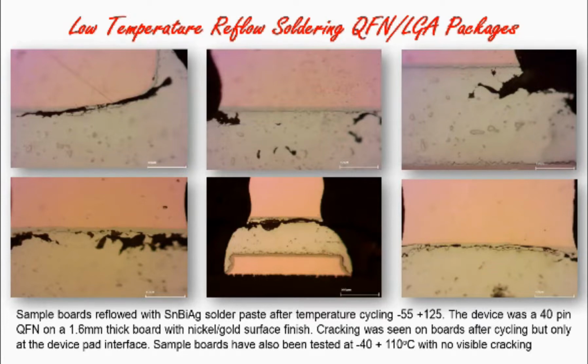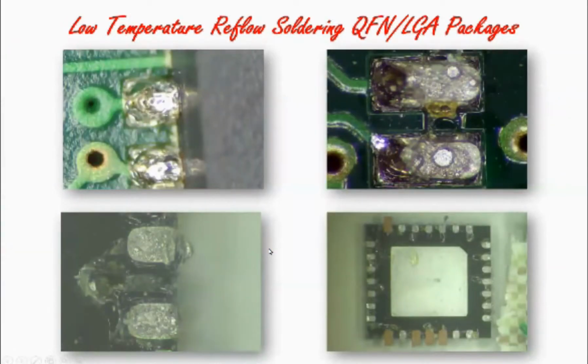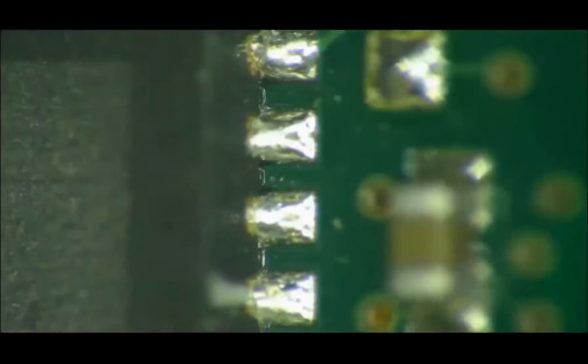But again, probably the most common reason for failure of low temperature materials is mechanical. It's not necessarily thermal expansion. But solderability has also caused me a couple of problems with low temperature materials. And this is just an example of a QFN which failed, where we were getting poor wetting on the pad terminations of parts. So again, I would urge you to look at testing parts if you are ever concerned with wettability or solderability of these parts, and it is still seen sometimes as a problem.